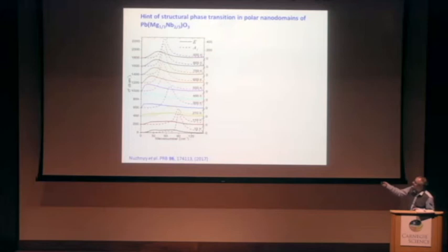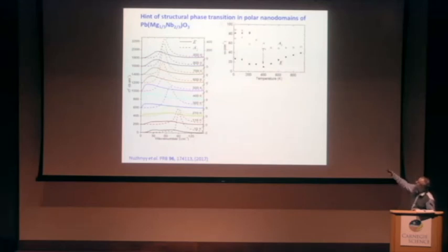Note that the A1 response is an underdamped phonon which shows softening and hardening with temperature, and the E mode is heavily damped or overdamped at some temperatures. So the E mode softens. This is the same mode seen in hyper-Raman spectra, and it shows a minimum at 400 Kelvin, and again some hardening. And the higher frequency component, in this case it is not this F2g mode interpreted in Raman scattering, but it is just the second component of the soft mode, which shows small softening. It is seen also in neutron scattering, and then the hardening.